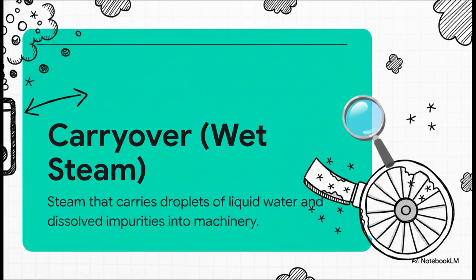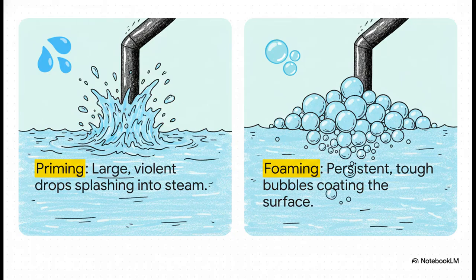It drastically lowers energy efficiency, and when that steam finally dries out later in the turbines, it drops those hard salt crystals right onto the high-speed turbine blades, severely degrading them over time. Carryover usually happens in one of two ways: priming or foaming.